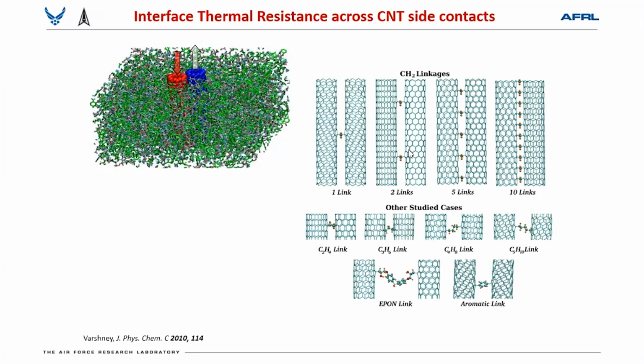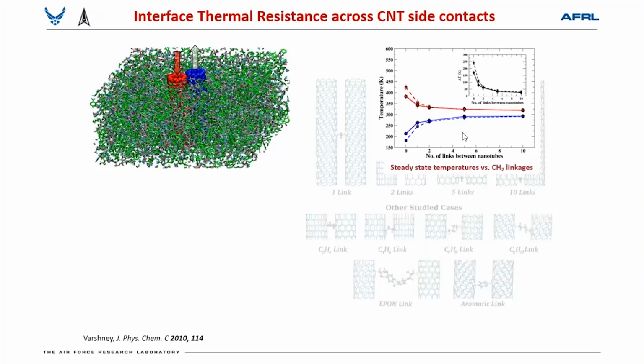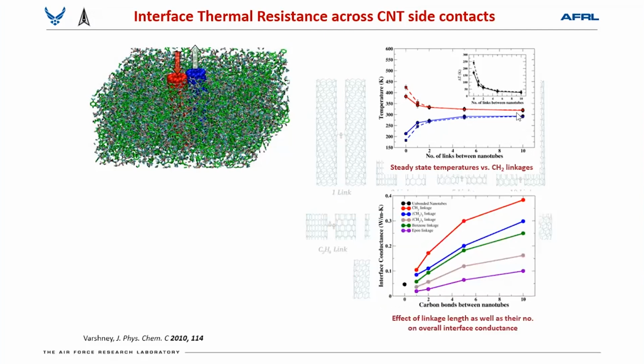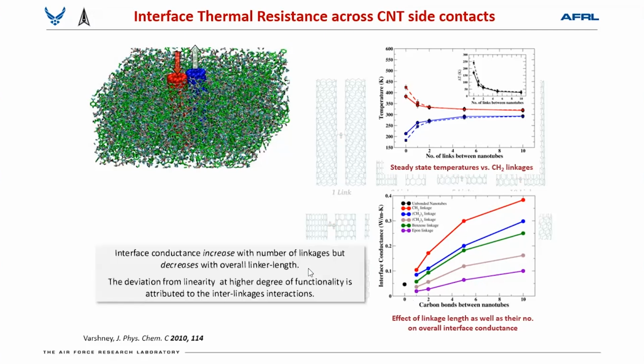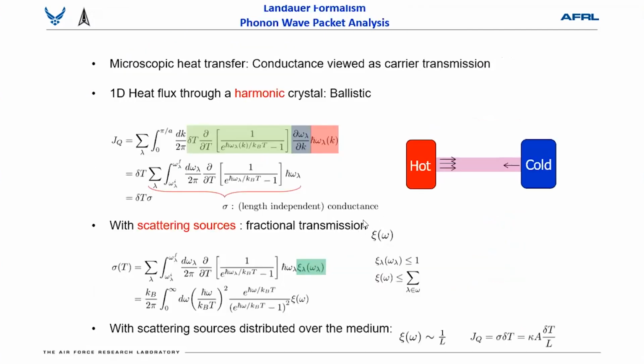So another option will be to functionalize these nanotube walls instead of van der Waals walls. You can functionalize with different molecules, either small molecule, big molecule, rigid molecule, and soft molecule. We look at those problems. Of course, as you increase the degree of functionalization, that improves the interface thermal conductance, but still we are not seeing it diminish to zero. That means there's room for selecting this molecule. So we look at different types of molecules. We find that smaller molecules and rigid molecules give you higher conductance than van der Waals properties. But still, there's room. How do you select these molecules?